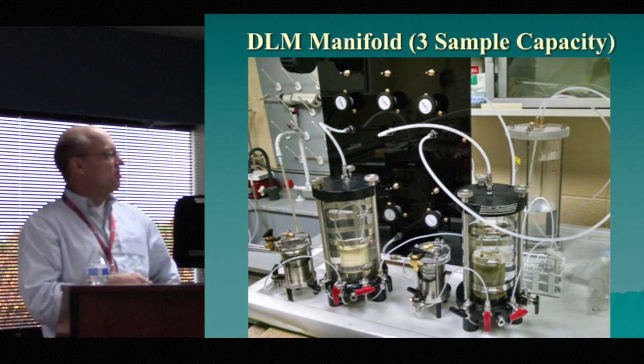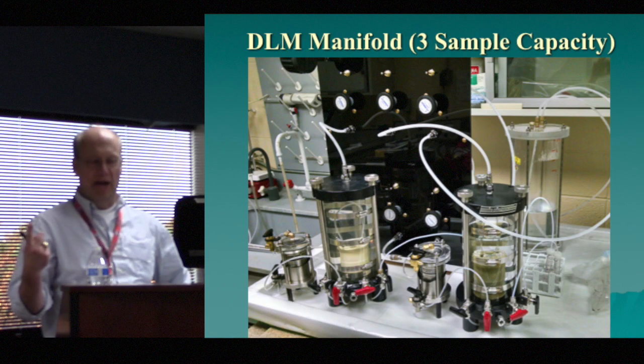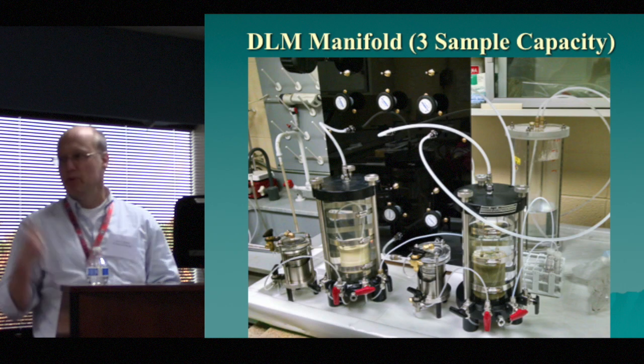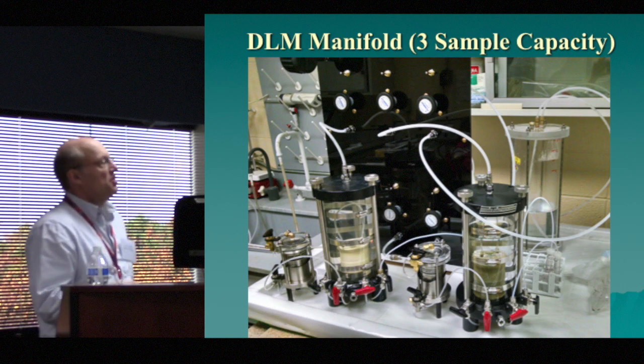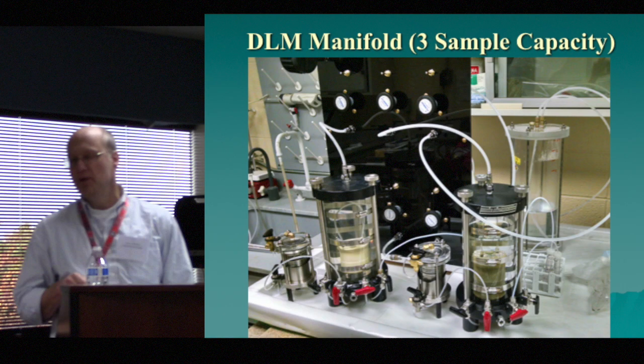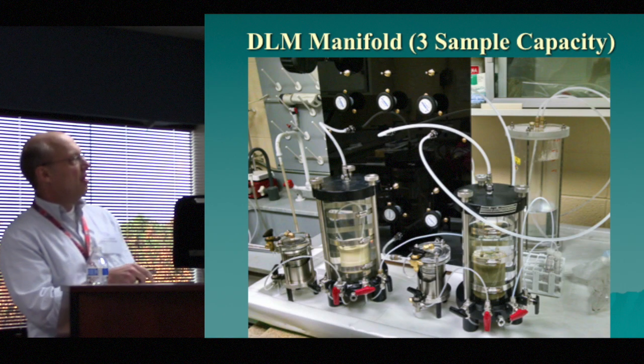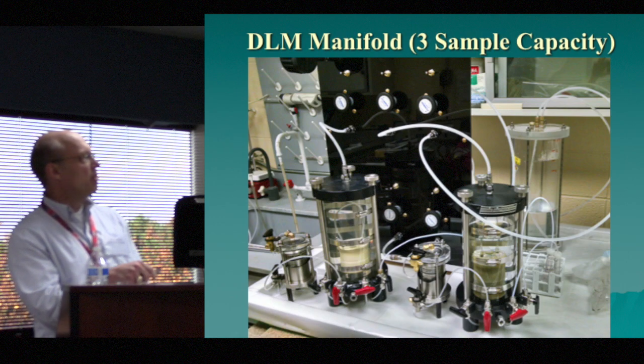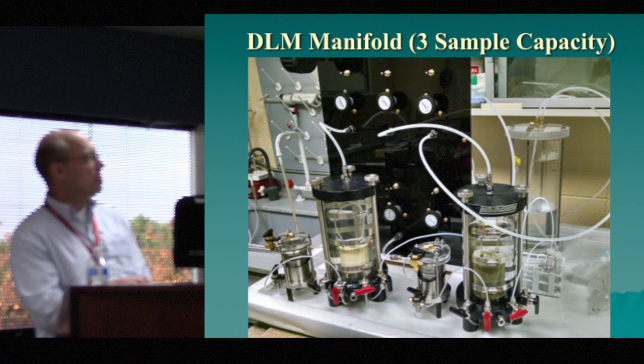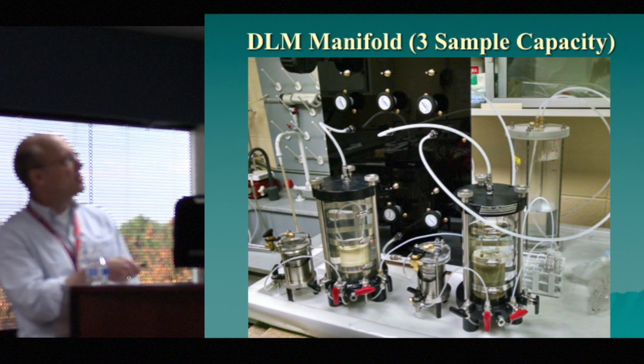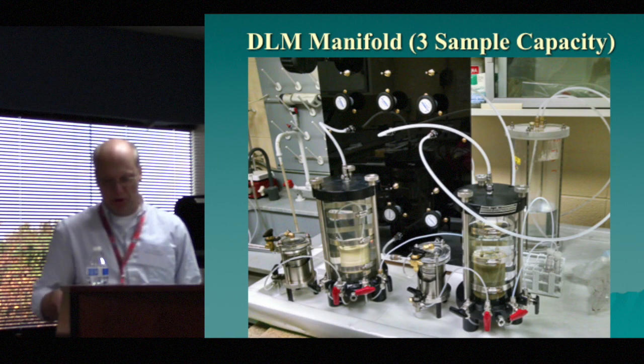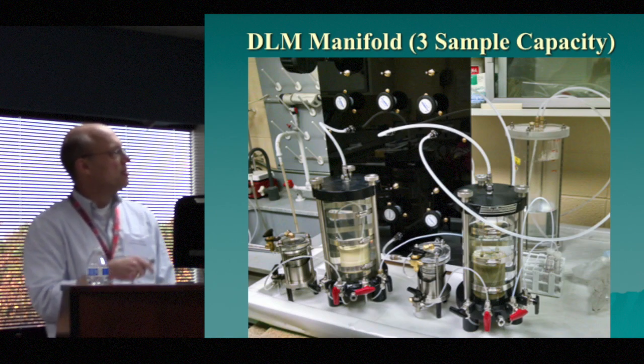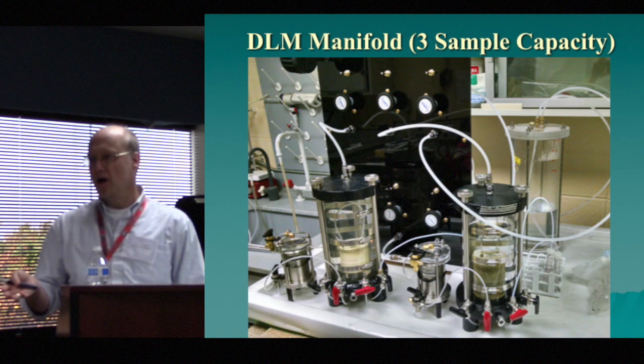So that was the first generation, and with one manifold, which is a very expensive piece of equipment, we could measure one sample at a time. So we went back and made a much simpler system. Essentially, you just need 2 valves per sample. We've only set up 2 samples here, but we have a valve for your confining pressure, a valve down here for your actual leaching pressure, and then we only have one pressure transducer because we have toggles that allow us to go through and measure the pressure on any of these given valves. So we can do 3 at a time for very, very low cost.